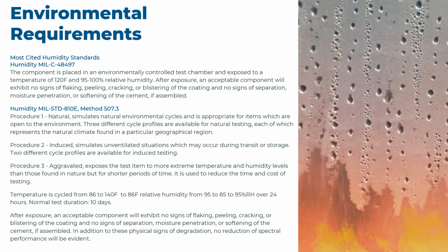So humidity standards. One of the most common ones we see is MIL-C-48497. And basically it's at 120 degrees F, 95 to 100% relative humidity. So basically after this exposure, you're not going to see any signs of degradation of the film. You're not going to see any crazing or spider webs. If you test adhesion, you should be fine. And you're not going to see any haze in the film, like the surface of the coating was breached and there's moisture underneath.